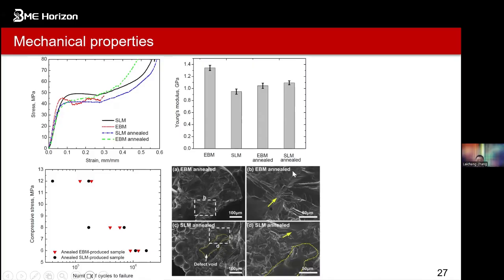But we can also see a large defect, greater than 100 micrometers in size, marked by the dotted part. It is also observed on the fracture surface of the SLM samples. Such defects would significantly decrease the fatigue life of the sample. That's why you can see here such a large gap, so large variations in the fatigue life.